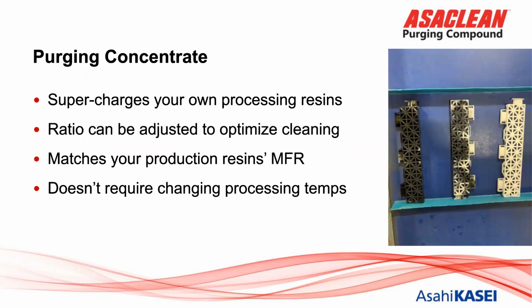Earlier this year, we launched Asaclean Plus, our first ever purging concentrate. The purging concentrate technology is derived directly from our chemical grades, and it's a way to supercharge your processing resin. You will only be receiving the active ingredients, and you can adjust the ratio depending on what cleaning is required, which does allow for some pretty amazing results when it comes to on-the-fly purging. Even though it is a concentrate, meaning that it's like our chemical grades where there is some soak time and possible temperature adjustment, it's possible that we can run this without requiring process temperature changes. So it's a pretty bright future for concentrates to have their place alongside chemical grades and mechanical grades.